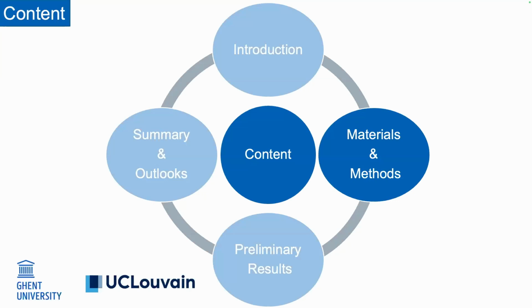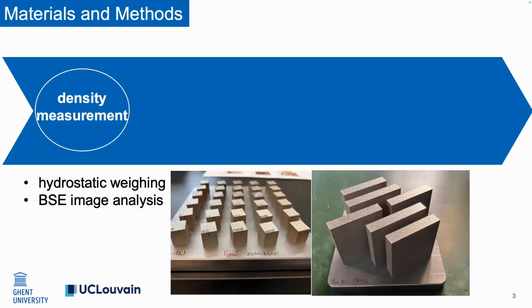Okay, going through the materials and methods, we printed different samples with different process variables, and we measured the density of these samples via hydrostatic weighing and some cross-section image analysis. We selected 2 batches of these samples. The first batch with the highest porosity fraction, and the second one with the lowest porosity fraction.